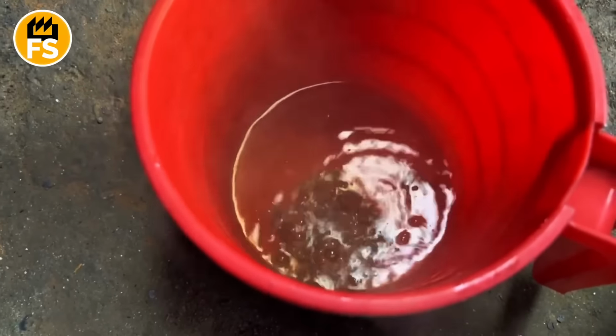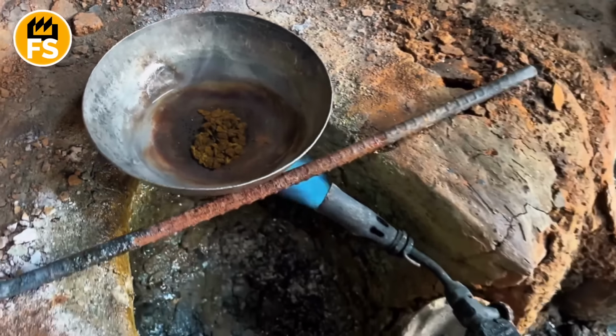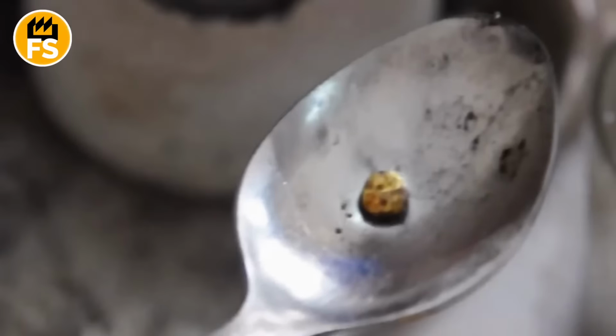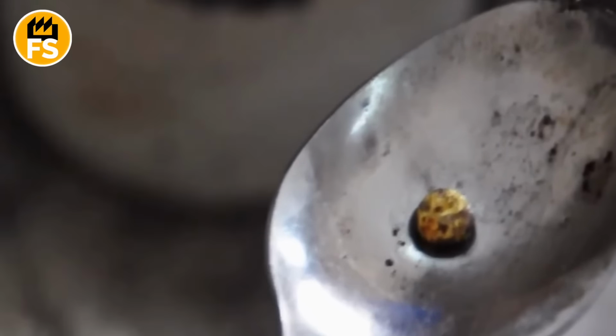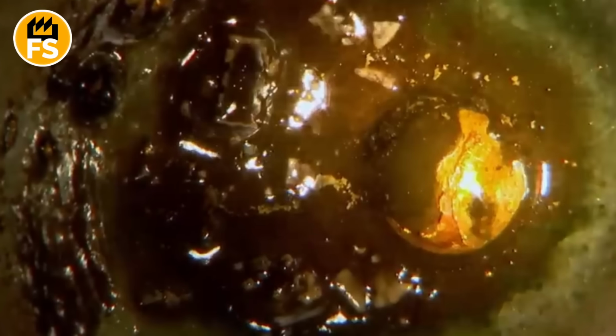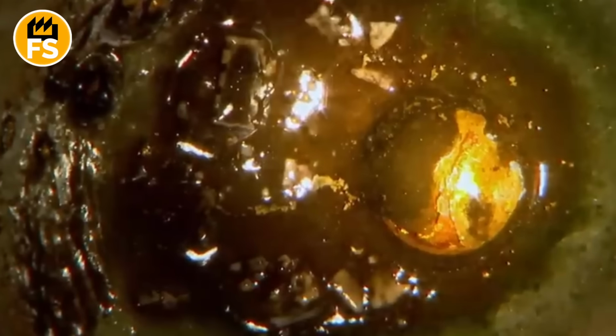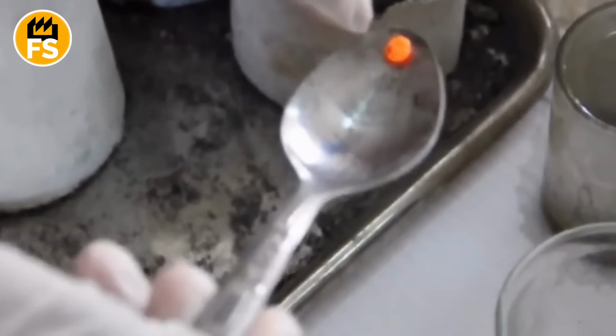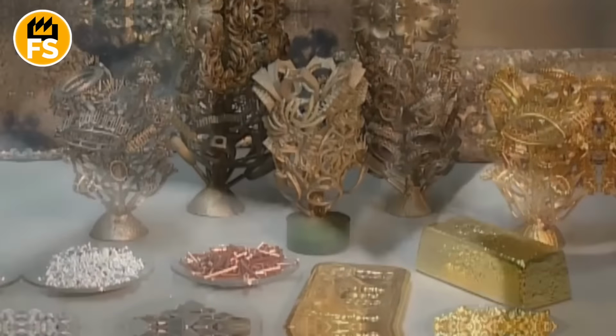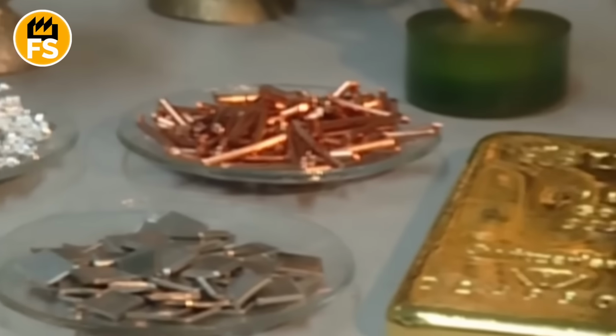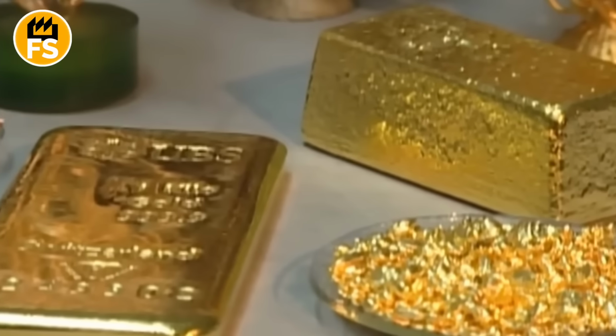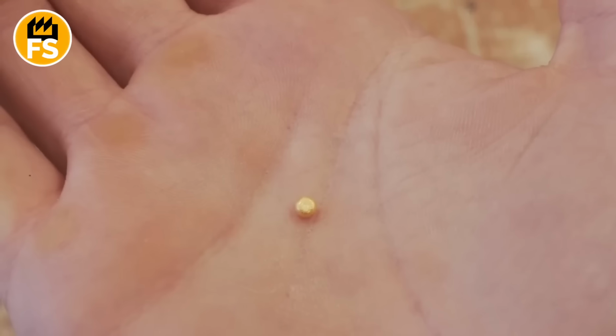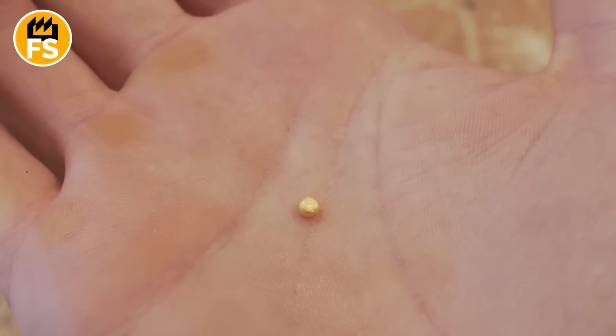Gold is precipitated from the purified solution by adding reducing agents. These compounds reduce the gold ions to a metallic state, forming a pure gold powder. The gold powder is thoroughly filtered, washed with distilled water to remove residual chemicals, and dried. The resulting gold powder is melted in high-temperature induction furnaces and cast into ingots or granules. At this stage, high-purity gold is already obtained, often 99.9%.